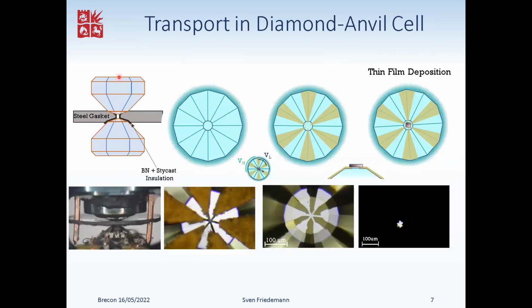So here again, the setup of two anvils with insulation and some metal gasket. In order to produce these electrodes, we take the anvil and we use a shadow mask, which has been laser cut, and sometimes we make the finest features simply with some fine wires. We evaporate through these shadow masks, and hence we end up with electrode configurations like this. So this is now an anvil that has been prepared indeed for hydride research.